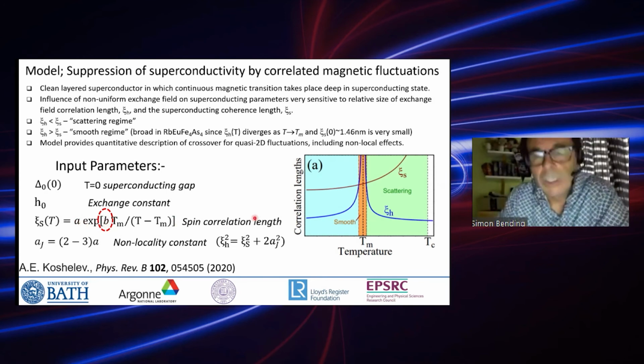So we control the spin correlation length via this parameter here, B. And we introduce the non-locality of the exchange field by this parameter A_J, a so-called non-locality constant, which is typically 2 to 3 times the interatomic spacing of the europium atoms in the AB plane.